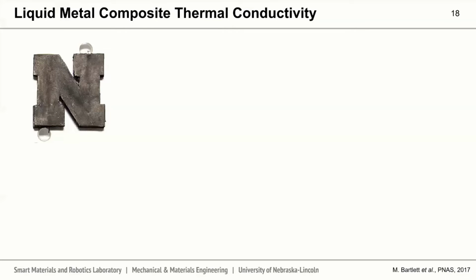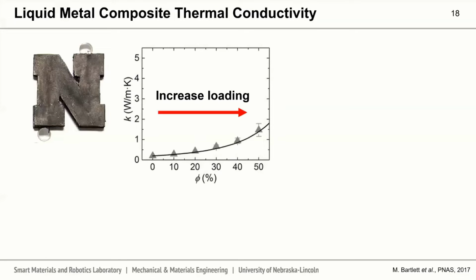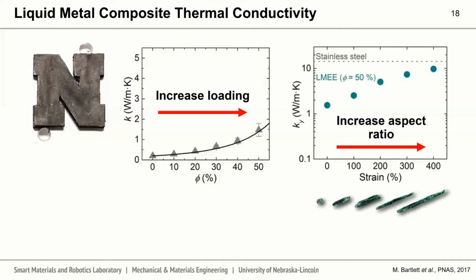We are interested in tailoring the thermal conductivity of these composites. At this point we have two knobs to do that: we can increase the loading of the liquid metal within the elastomer composite to see an increase in thermal conductivity, or we can increase the aspect ratio of the liquid metal filler within the composite, which increases thermal conductivity in the direction of that change in aspect ratio.